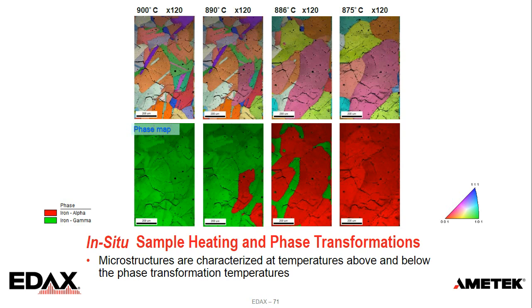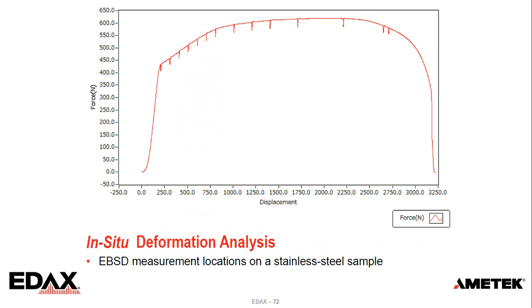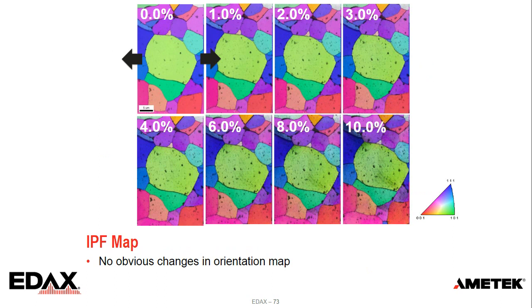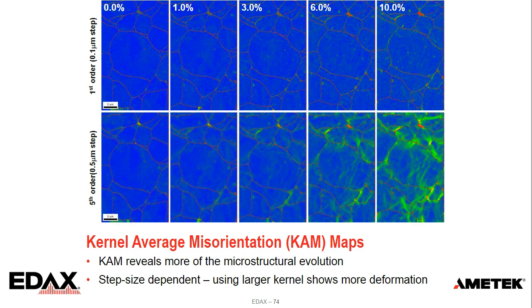And we can also do in-situ deformation analysis. So this is just an example of using a stage where, when we start to yield, the material is sort of our zero point. You can see the little notches where we stop the deformation and measure the microstructure at each point. And we can see with the amount of deformation how the microstructure evolves as a function of deformation. If we look at the orientation map, you'd be hard-pressed to say you see a huge change in these particular maps. If we look at it with our KAM, or kernel average misorientation map, we start to see it a little bit, and that top line shows our first order kernel. The bottom line shows the fifth order, so we're stepping out further.